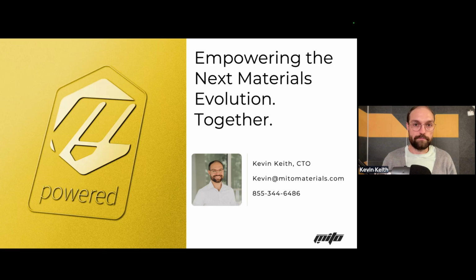All right. Next question. How does incorporation of graphene or graphene oxide into high-density polyethylene, HDPE, and linear low-density polyethylene, LLDPE, influence their thermal conductivity? And what mechanisms are responsible for the observed enhancements? I can't answer that last one because that's trade secret, and I'm pretty sure my boss would have my head on a platter if I do that. In regards to thermal conductivity, I'll just generalize it in PEs. Graphene oxide, you'd have to make it a powder, and then it would not be good. It would actually become more insulating. If not, you would only get maybe a couple percentage points increases. That's because of a lot of different aspects of graphene oxide that we've been able to correlate to.